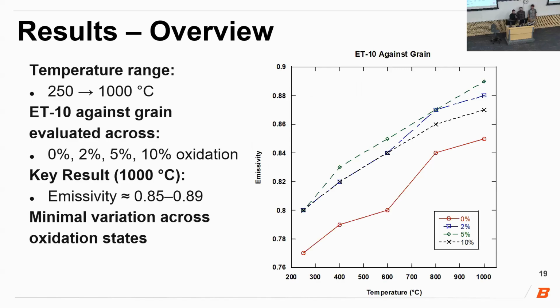We have tested 24 different samples with 2 different orientations, totaling 48 data sets. We've chosen ET10 against grain orientation to show. This chart shows the relationship between emissivity, temperature, and oxidation.